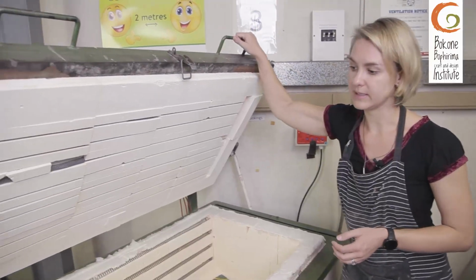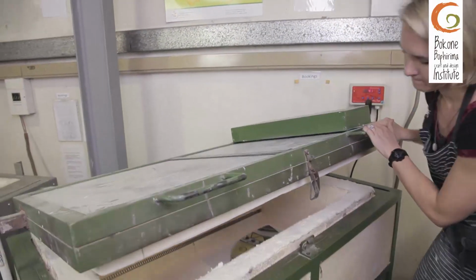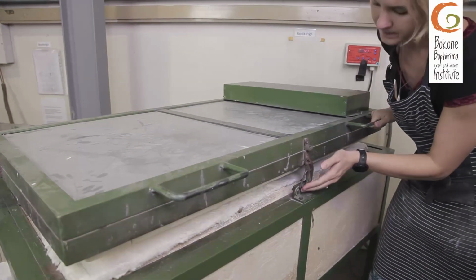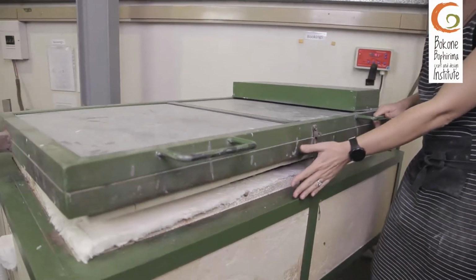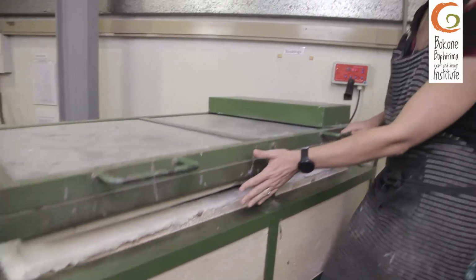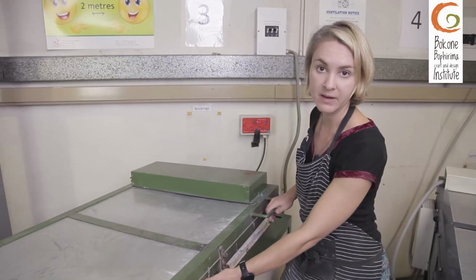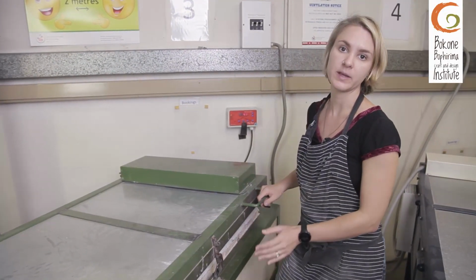I'm going to bring the kiln lid down. I'm going to leave the kiln lid open for the first 100 degrees Celsius to allow any moisture to escape out of the kiln, and then I will close it when we reach 100 degrees Celsius.